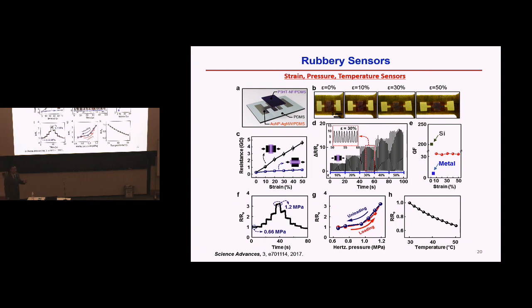If we compare our device with the most commercially available devices, the key factor here is the sensitivity of the strain sensor, which is the gauge factor: the relative resistance change over the strain applied. The best is lightly P-type doped silicon, with the highest gauge factor of 200, but silicon is a brittle material. The operation zone is about 1%, then the material eventually fails. So you can only apply it to cases with very tiny mechanical strain.